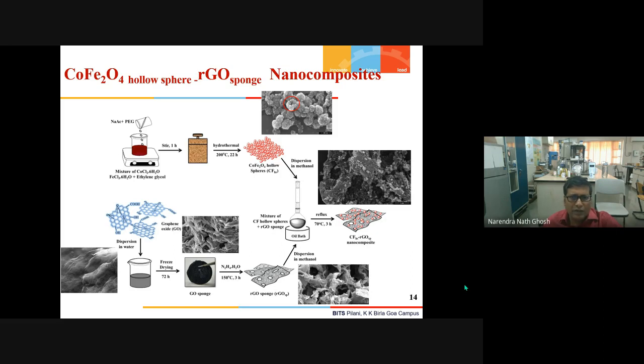So here, we made the cobalt ferrite hollow sphere in a reaction mixture consisting of ferric chloride and cobalt chloride. We use sodium acetate as the pore-forming, sphere-forming agent, with PEG and ethylene glycol. Then we mix this mixture, put it in a small hydrothermal reactor, and treat it at 200 degrees Celsius for 22 hours, and then we collected the spheres.